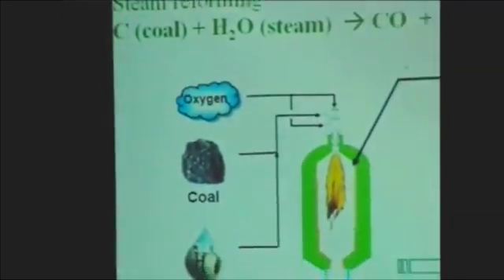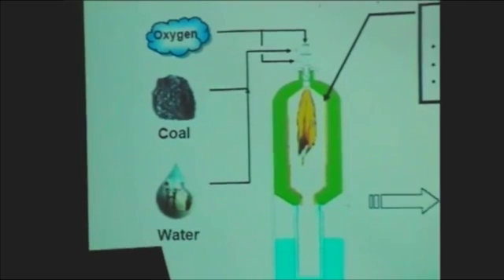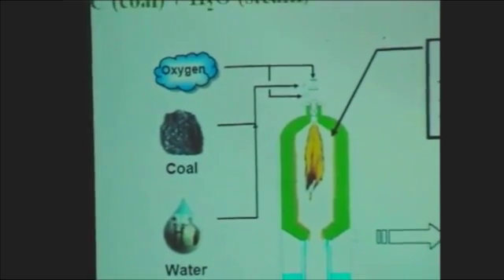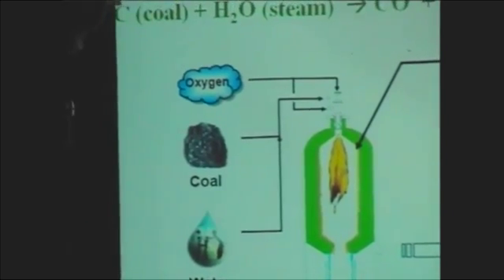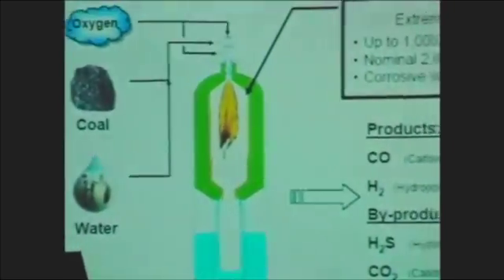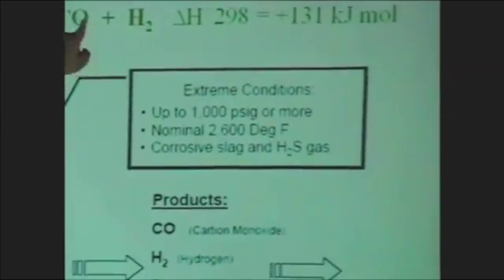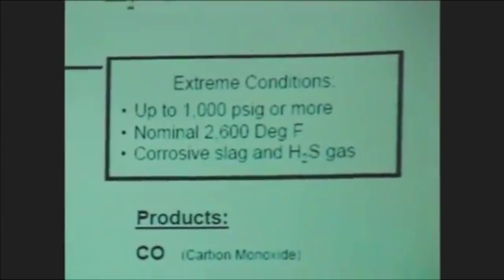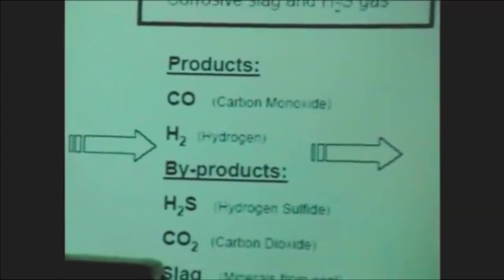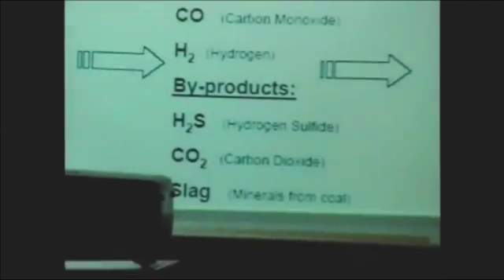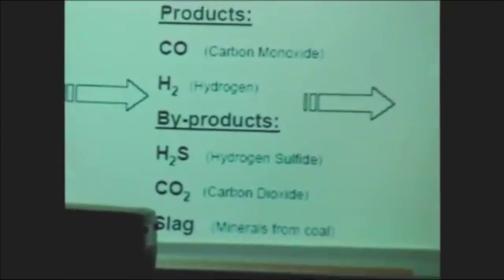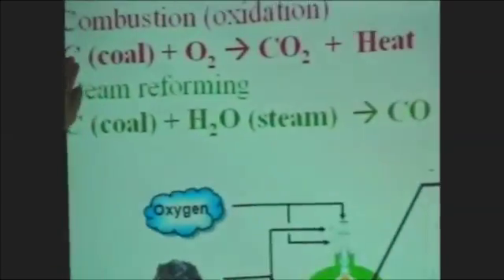In fact, Peter proposed to generate hydrogen from the steam reforming reaction and try to separate the combustion and steam reforming reactions. If you mix these two reactions together, the excess oxygen can oxidize the product of the reforming reaction. So most of the time, you might be better off separating the combustion stream and the steam reforming stream.